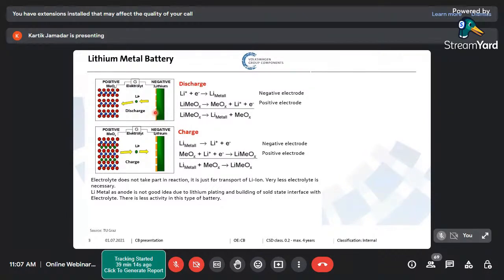Why? The reason being that when lithium was coming every time during the cycle and getting deposited on the lithium metal, it was not getting deposited uniformly on the lithium metal.